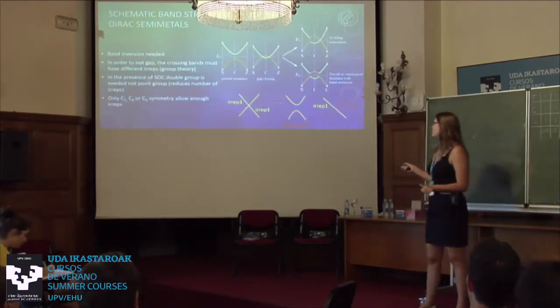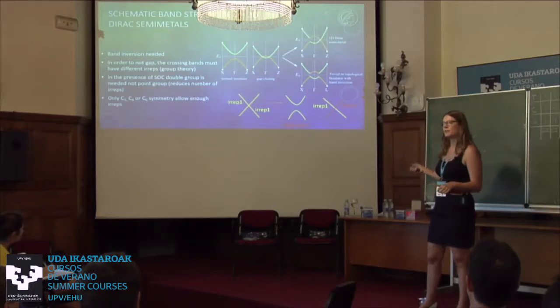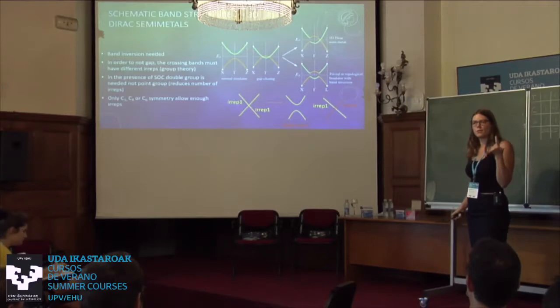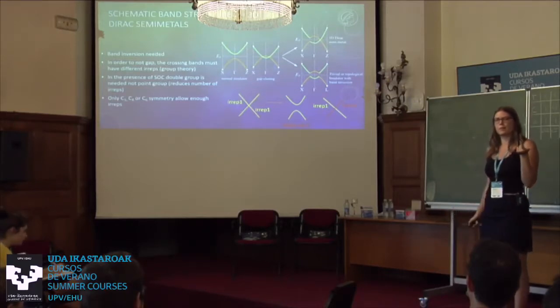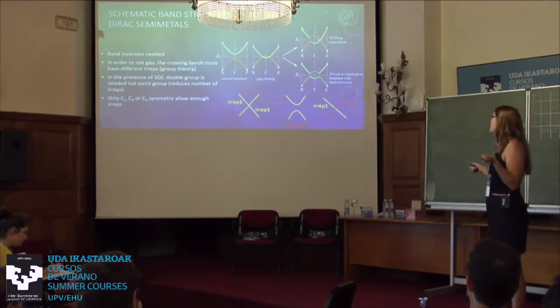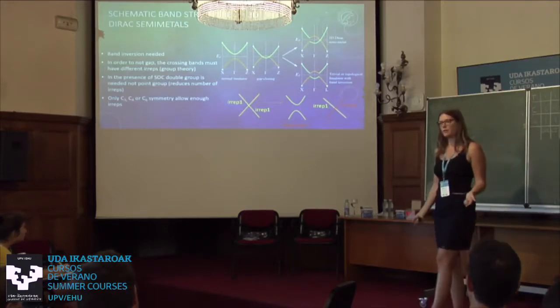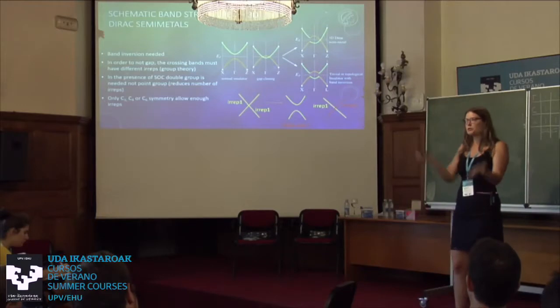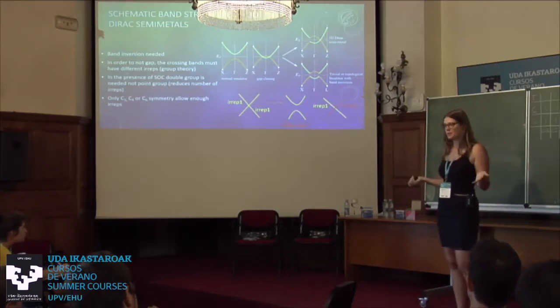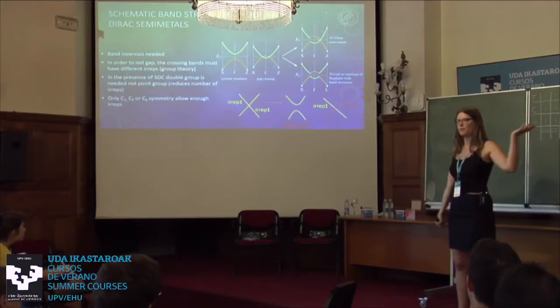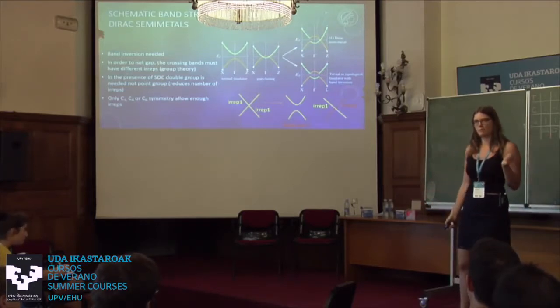Then this is a charge balanced band structure. We started this process from a charge balanced compound, so we want to have the correct electron count. We want to look for a charge balanced material, and then we want to have a zero density of states here. We just want to have the Dirac crossing there. So we need a good ratio between electronegativity difference and spin orbit coupling, so that we don't have a metallic compound, but we also don't have a wide band gap insulator where we would never have a band inversion.